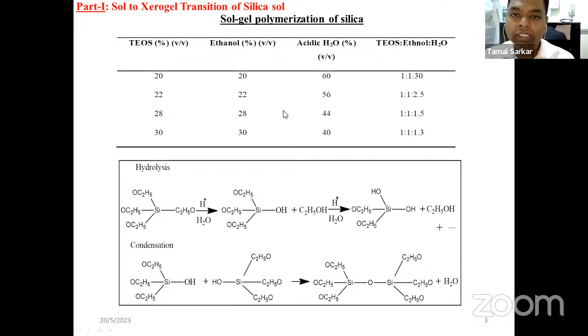In this work, silica gel was prepared using the sol gel polymerization method. I described earlier that TEOS, tetraethyl orthosilicate, is the main precursor for this silica, and I had taken it in different percent volume by volume ratio, starting from 20, which is lower, and ending with 30, which is higher. Two additional solvents are also used, which are ethanol and acidic water, which has a pH close to 1.